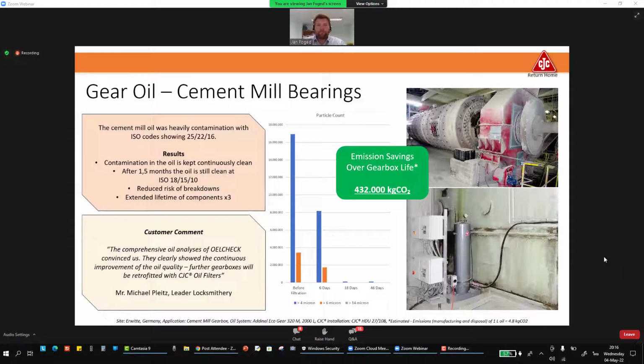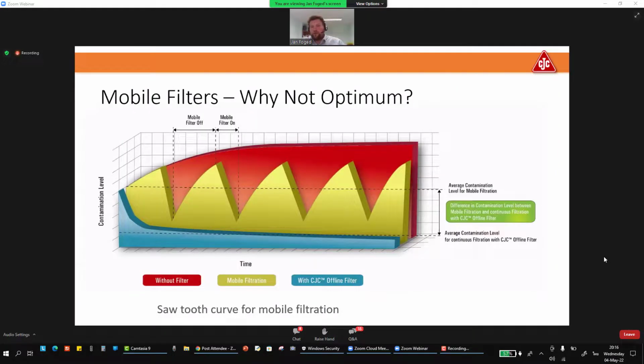So it's a simple kit to reduce your emissions just by maintaining your oil instead of changing your oil. To give an example of a mobile filter, a lot of people say we'll put a filter on for a period of time and then we'll take it off again. Here you can see the comparison. The blue is continuous offline filtration. The yellow is a mobile filter, and you can see the peaks going up and down. When the filter is on, it removes the dirt and brings it down to a good level. The minute the filter is off, it goes up very high, very quickly again. And the red curve shows the amount of contamination continuously with no filter on, and you can see that's very, very high.